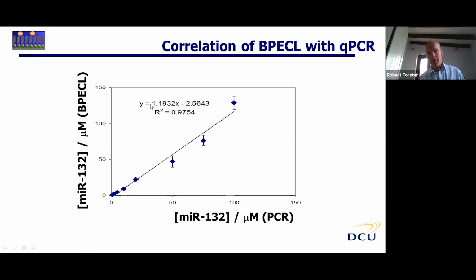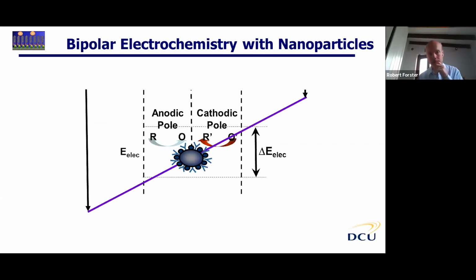We don't get a perfect correlation. A perfect correlation would be a slope of 1 and an intercept of 0. Our slope is a little bit higher, but it's reasonably close to 1. If this data point was excluded, we'd get a slightly lower slope, closer to 1. Relative to the scale of the y-axis, the intercept is approximately 0. So we really do get quite close to a direct, unbiased correlation between qPCR and the bipolar ECL.